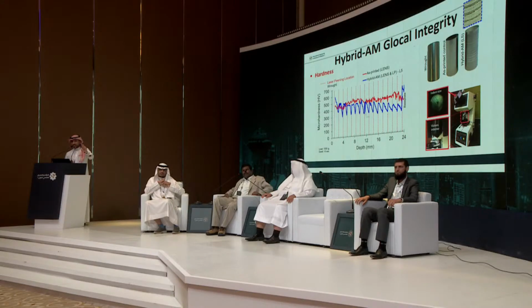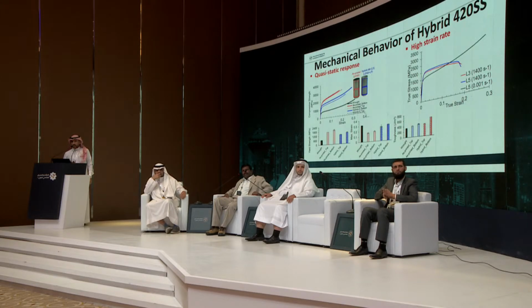The blue color here indicates that the hardness can be changed across the surface of the materials. Okay, if that is actually happening, what am I getting from these hardness changes and microstructure changes? We did mechanical properties characterization, and we did quasi-static performance, and then we did high-strain performance, like ballistic performance, when you have a bullet coming out from a gun and hitting an armor. And this got us a very interesting result.